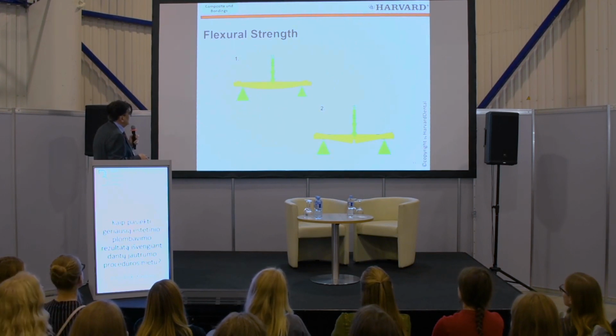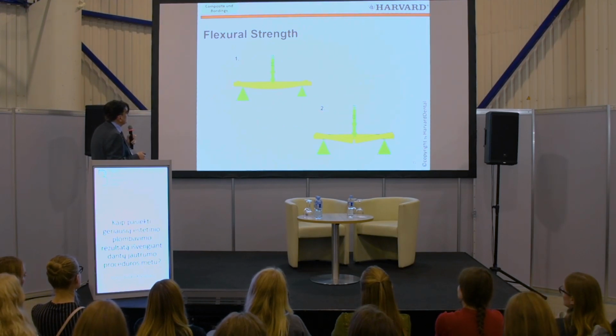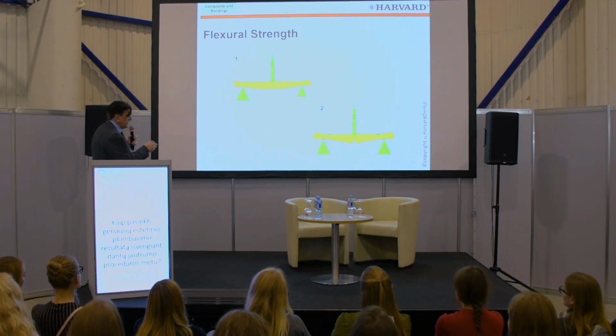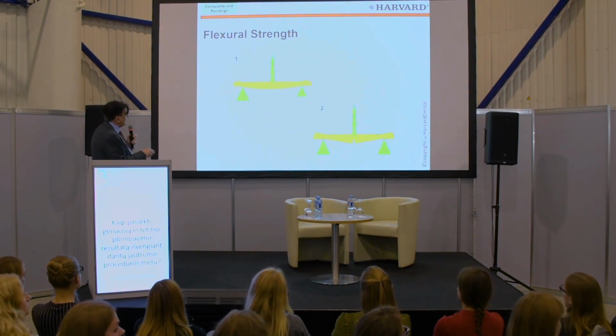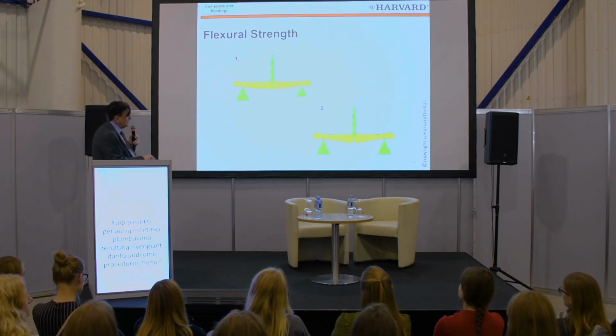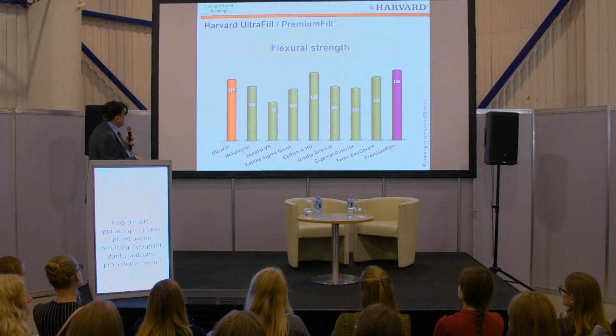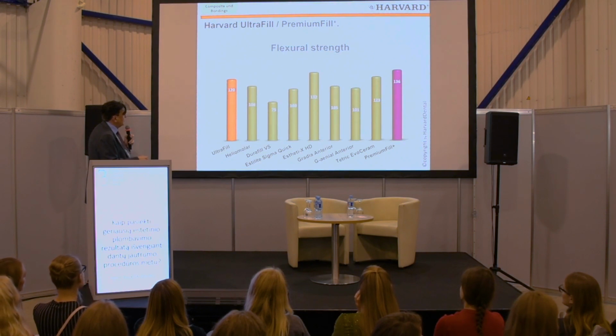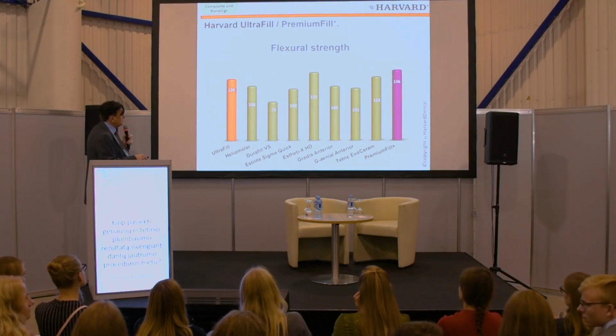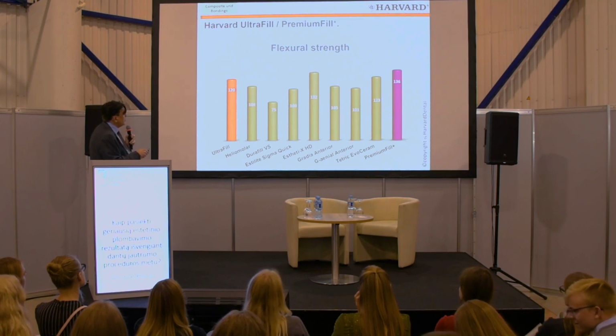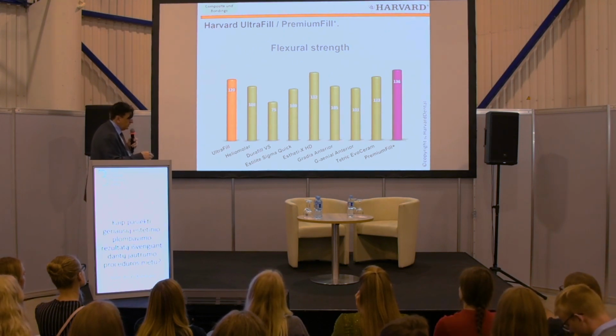Now, I don't know if this helps you as a dentist. The flexural strength is when they take a piece of the composite filling, apply a load, and see when it will break. It's more for the research dentist than for the clinician. But just to tell you that, for example, it's 120 megapascal, and we have another, Premium Fill Plus, at 136. So it's quite strong compared to the other competitor.